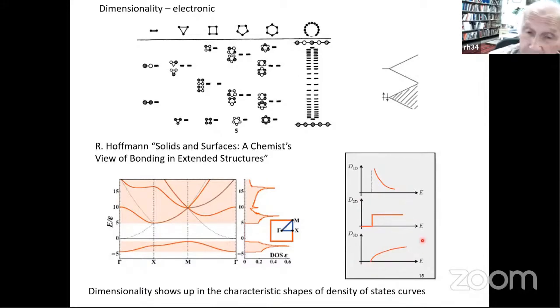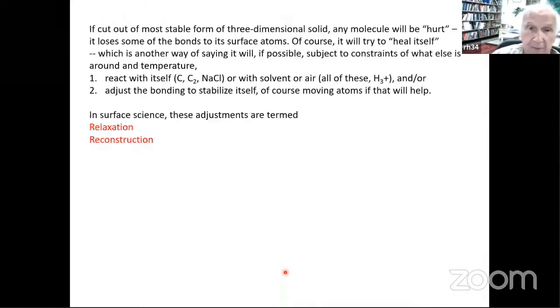You can get all kinds of shapes from superposition of this. But when I see a density of states without knowing anything, when I see a sharp rise, and then that looks to me like the middle one of these, I have an idea that there is 2-dimensionality in this structure. So this is another way. And what's very interesting is those cases, which come in more frequently under high pressure, where the electronic dimensionality differs from what you would conclude on the basis of structure. They are few, but they are very interesting.